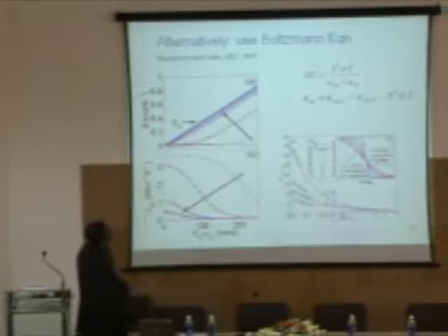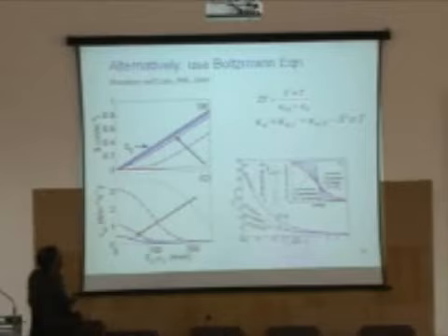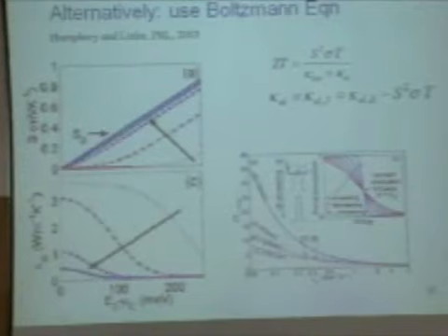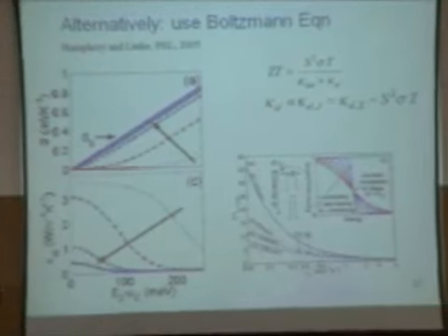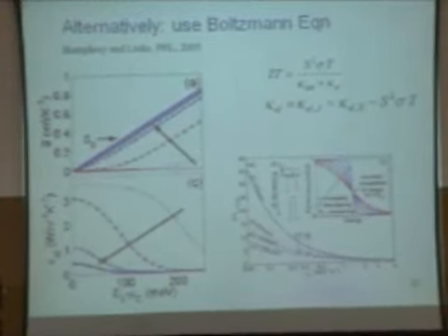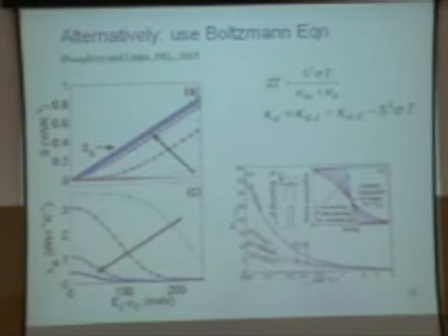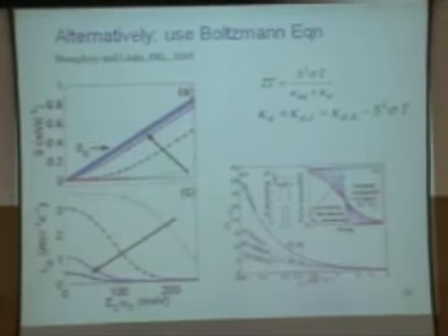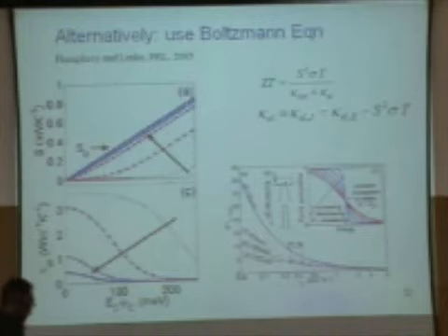The electronic thermal conductivity as a function of J has 2 pieces. What you find is that if you change the chemical potential along with the temperature, demanding this to be a constant, this is what the calculation is. Then you find that ZT here, as you tune the energy levels, you find both. One thing you find is that the electronic thermal conductivity goes to 0, which means this guy exactly cancels that, and you get enormous ZT. So this is an idea which maybe 20 years from now might be feasible.